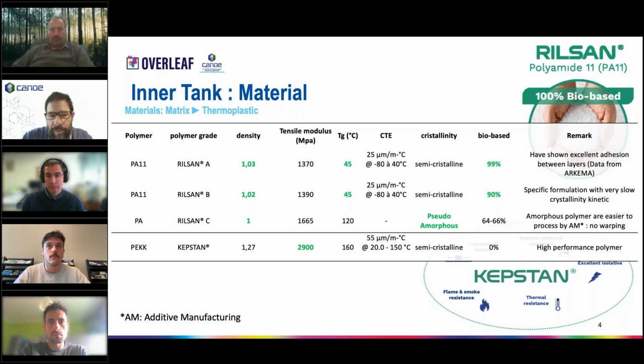And then for all candidates, you can see a column with the expansion coefficient, the CTE. It's pretty important to keep this value in mind, because at very low temperature, when we mix these organic materials with some reinforcement, we have to be careful about the choice of the reinforcement. If they have a different CTE, it could lead to some defects, some micro cracks in the materials. And as you can see, polyamide is twice lower than the PEKK material.